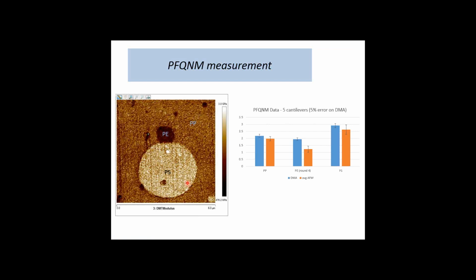Bede is going to talk in more detail later, but this is a PeakForce QNM measurement on our three-polymer blend, and we're mapping now the modulus, comparing the bulk DMA in blue with the AFM measurement from PeakForce QNM in orange, doing quite well.